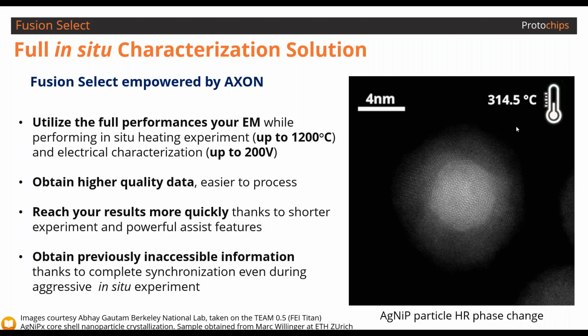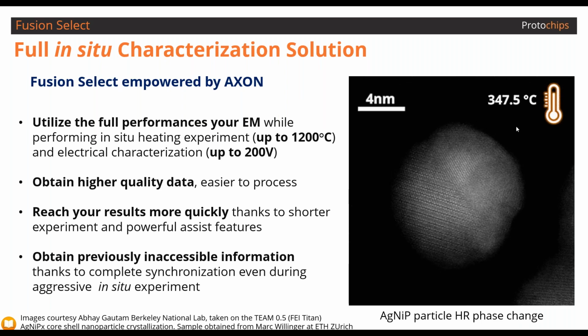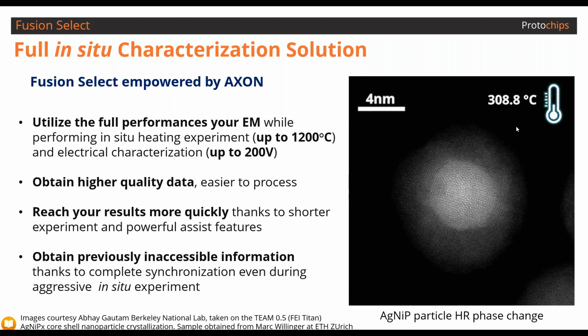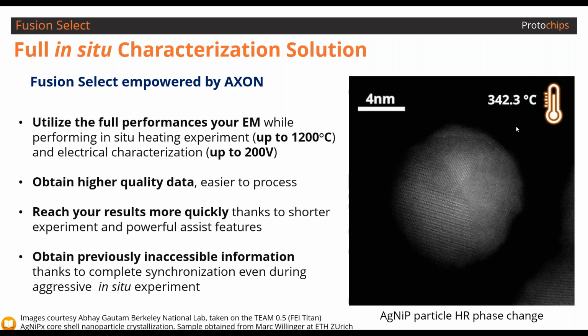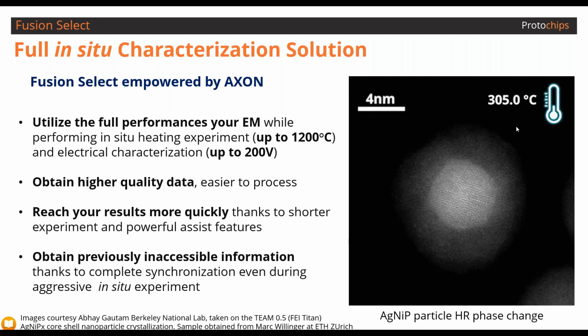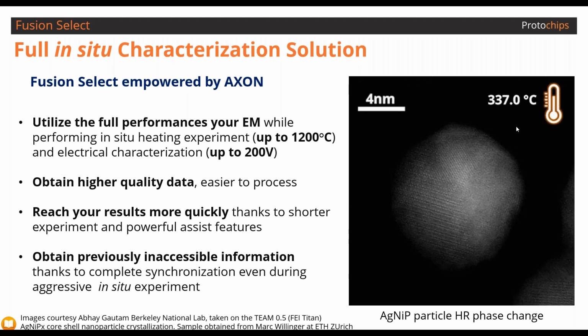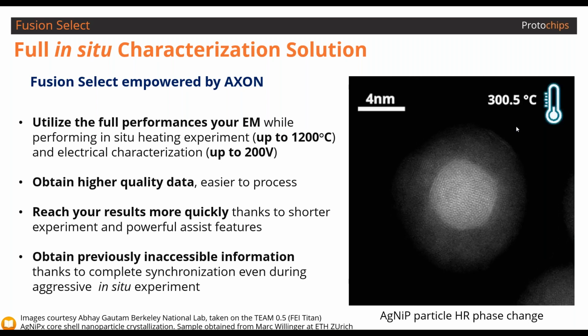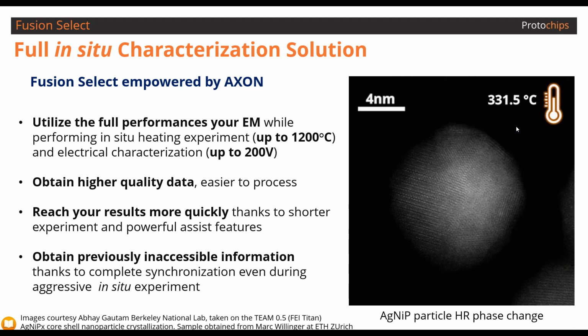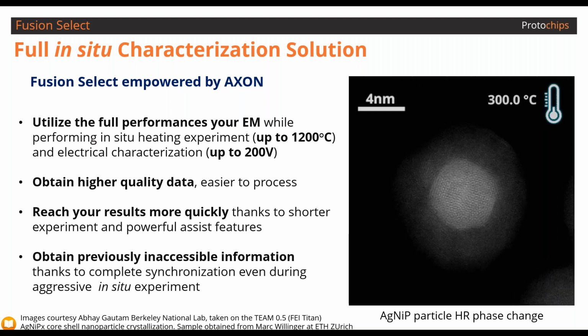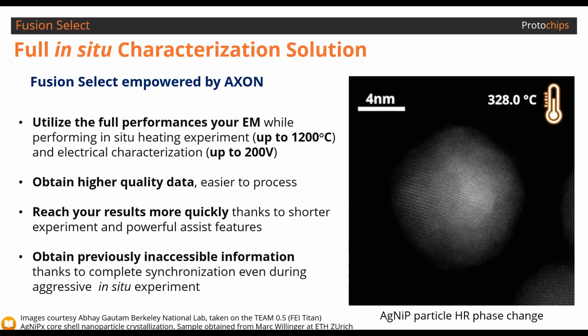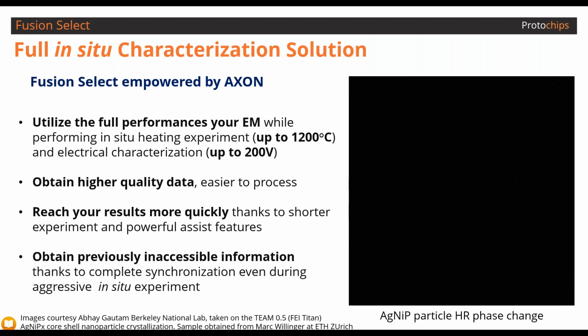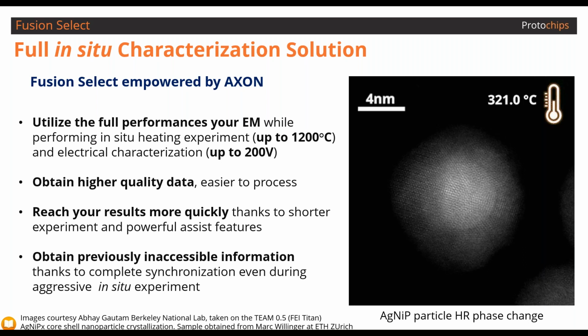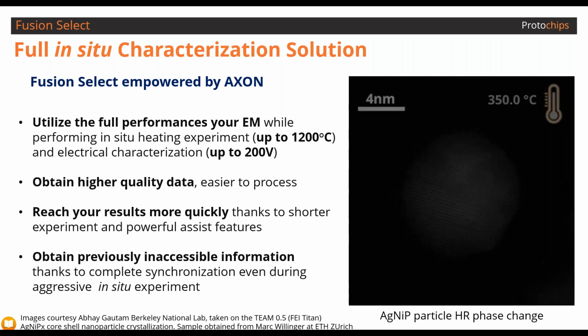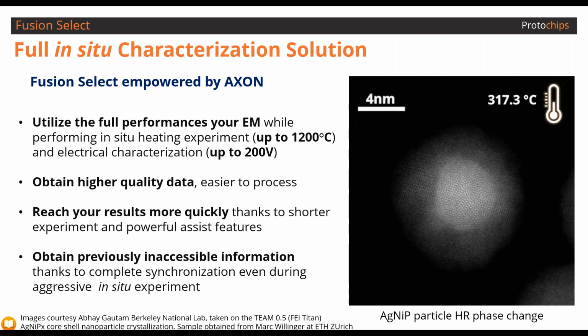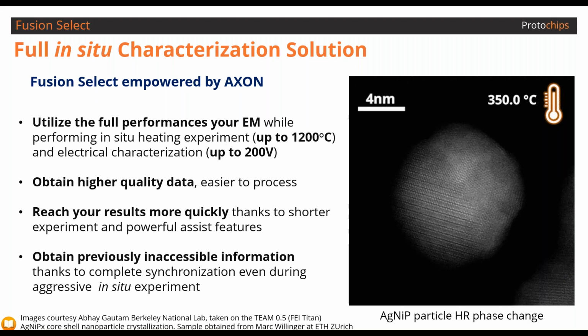So what does a final result look like? In this example, this is from Mark Willinger at ETH in Zurich. It's a core shell silver nickel phosphorus particle. And we've been able to observe extremely rapidly, during the first test, the phase change happening at atomic resolution during a live heating stimulation. So during an active change of temperature, the region of interest was perfectly maintained around the particle. The field of view was perfectly maintained around the particle, and we could witness the entire procedure at atomic resolution. And this is the kind of result which is unprecedented and is impossible without the combination of the Fusion Select system empowered by Axon.